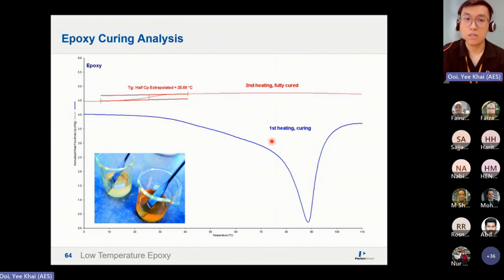Then, of course, like what I mentioned just now, this is a low temperature epoxy curing material. When it's not cured, it's going to heat. Curing, remember I showed just now, is a chemical process, it is irreversible, and it is always exothermic because new bonds are being formed. So you only get the curing peak once. Then you cool it back down, and when you heat it up again, now you can see your Tg. Why? Because thermosets or cross-linked materials are always amorphous, hence Tg. And when it is fully cured, you will not see the curing peak anymore.